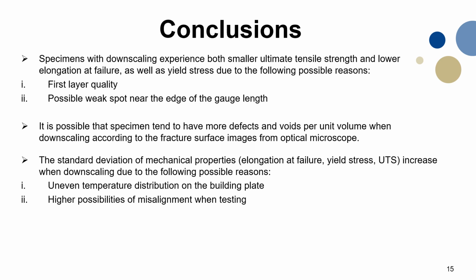And the standard deviation of mechanical properties like elongation at failure, yield stress, and UTS increases when downscaling, due to the following reasons. First could be the uneven temperature distribution on the plate. When we printed all the samples, for each test we have at least 5 of them, so we laid all of them on the printer to print. That might cause some uneven temperature distribution on the building plate.